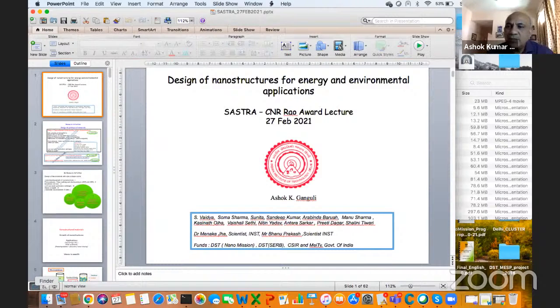Yeah, yes. Because in the theoretical study, when we are drawing the energy levels, we are drawing as if you have two very smooth walls against each other. And then the theoretical diagram shows the conduction band of one and the conduction band of the other. If you have particles, then that clear structure will not be there all through the material. So you will have heterogeneity even at the local level in the band edge. You will have a local density of states very different compared to the overall thing that you have actually calculated, assuming that the two semiconductors are very segregated and there is a very clear interface.